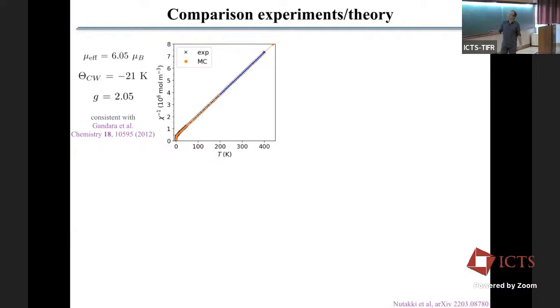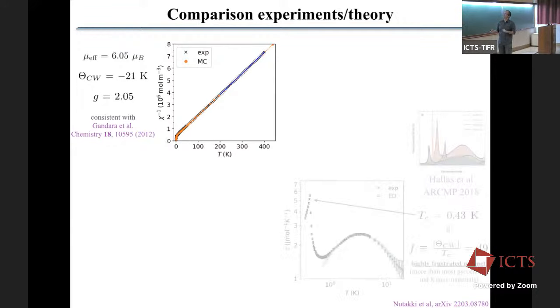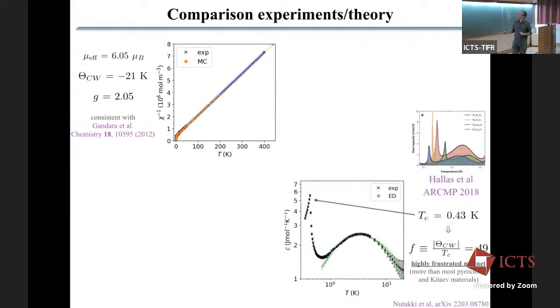And this is also consistent with one previous experimental measurement on this material for the Curie-Weiss susceptibility, which also found something around -20, -30 Kelvin. So this is under control. Then if we measure the specific heat as a function of temperature on the log scale here, the specific heat has a broad bump here, and then a peak at low temperature. And so the peak happens at around 400 millikelvin. So that's a thing to keep in mind. The Curie-Weiss temperature is around 20 Kelvin, and the transition temperature is at around 400 millikelvin, which means the ratio of the two gives you around 50. So for the frustration. Okay, very good.